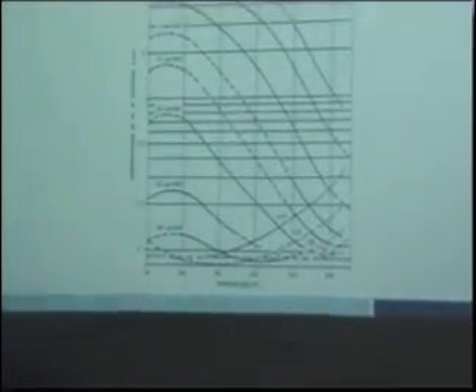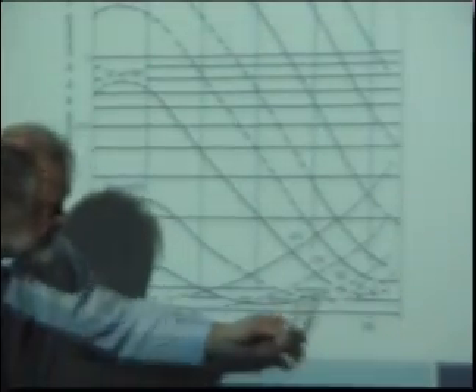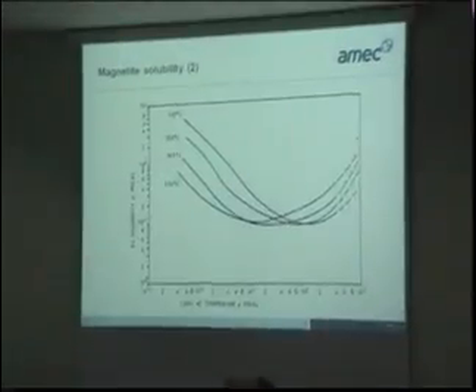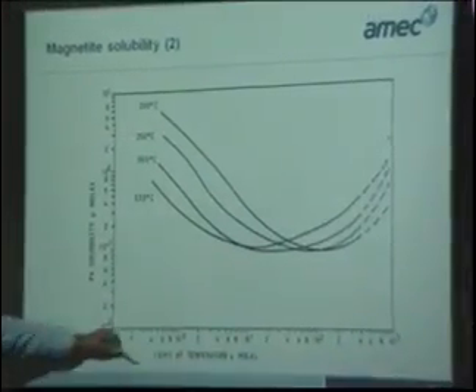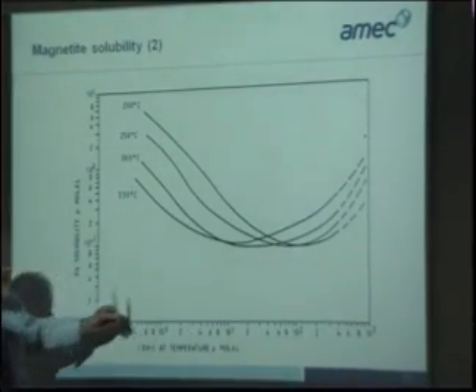So we've got ion concentration, and we're only interested in this region really, between 280 and 330, because that's where we're operating in the core. If you imagine the inlet water in the core at about 285, as it goes through the core, it increases in temperature and comes out at about 290, 293, something like that. So you can see here the slope of this line could be negative or positive depending on which pH you're operating. If you were to plot that the other way round, in other words, if we just take a series of temperatures and plot the solubility against the pH, we can get a better picture of what's going on.